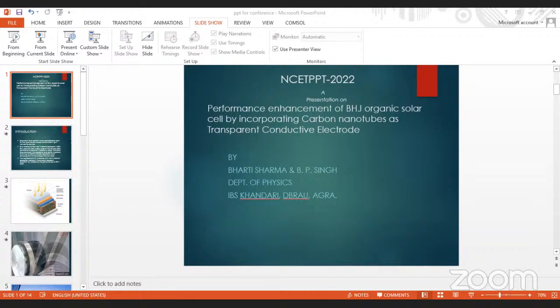Here we have modeled and simulated the NFA-based organic solar cell using CNT doped with molybdenum trioxide as a TCE to optimize photovoltaic parameters such as VOC, JSC, fill factor, and power conversion efficiency, which are the important parameters for the device simulation of organic solar cells. These are carbon nanotubes, like single-wall, double-wall, and multi-wall carbon nanotubes. Here we have used a mixture of these. This is the materials and method; I would like to skip this.